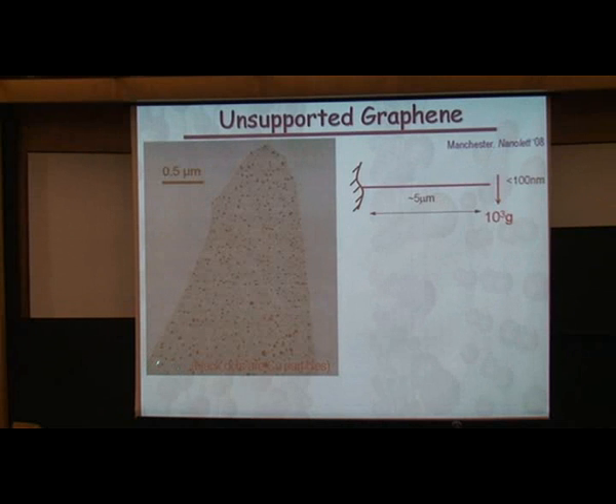This is a view from the top or from the bottom of a flake of graphene, a single layer of graphene, which is supported from this side, and it stretches 5 or more microns away. It's 1 atom thick, and it covers all the area. If you look at that aspect ratio, it's like a piece of glass which extends over a few kilometers and covers a bridge. In addition, it's loaded with copper particles in this particular case, and you move it. When you move a nanomechanical system, its shock acceleration usually exceeds 3,000 G. And still it doesn't roll, still doesn't bend.